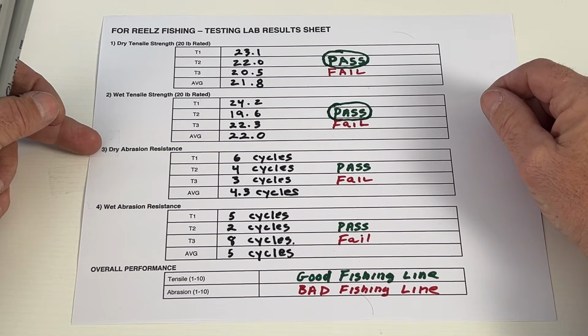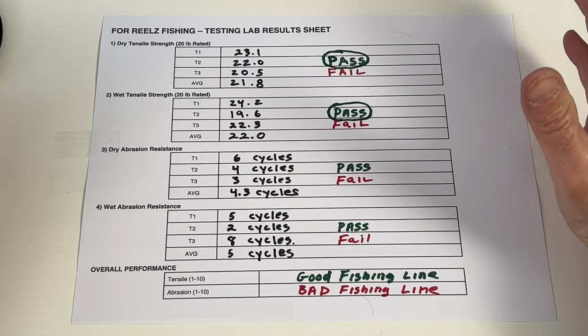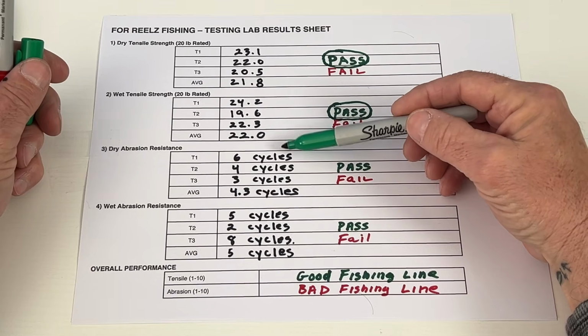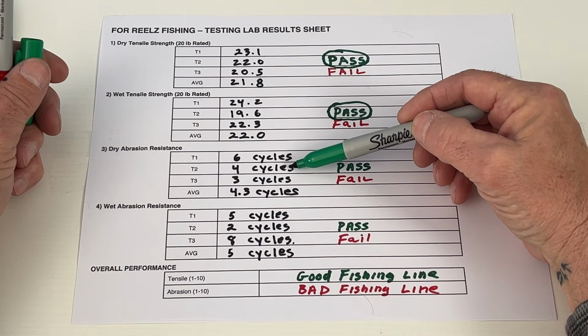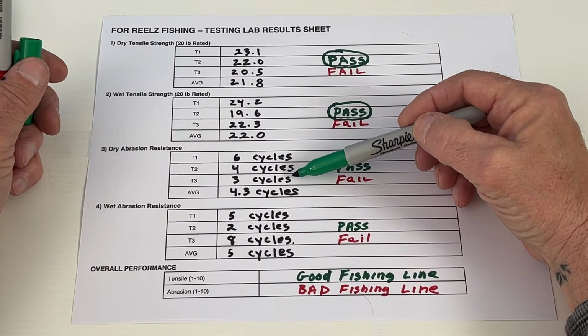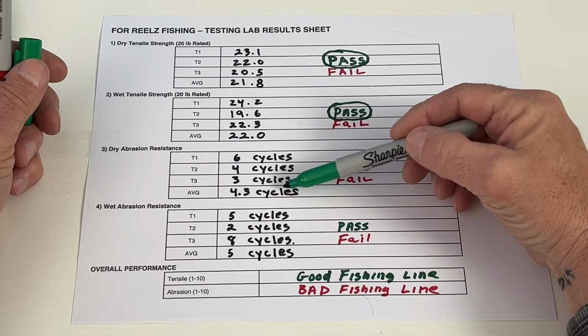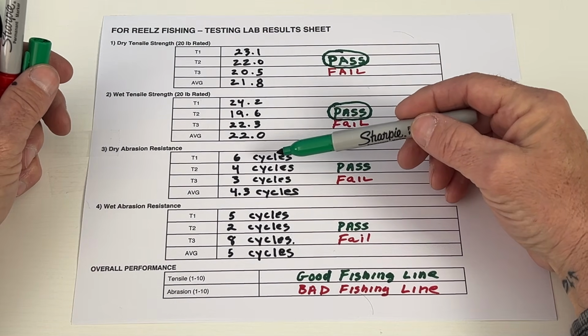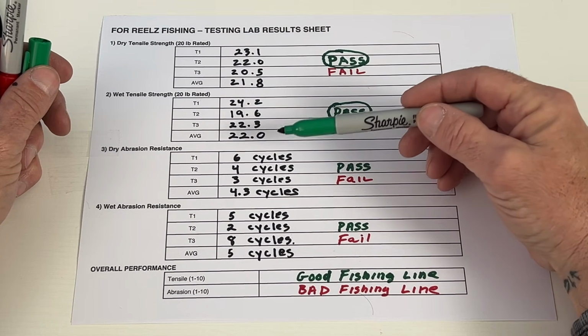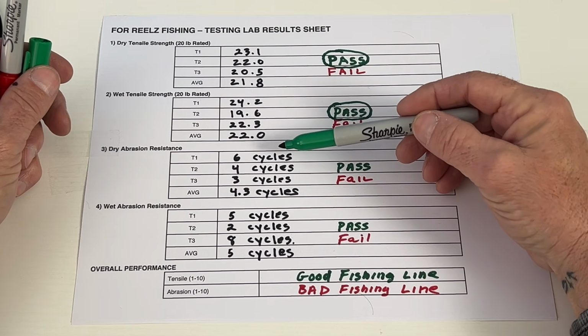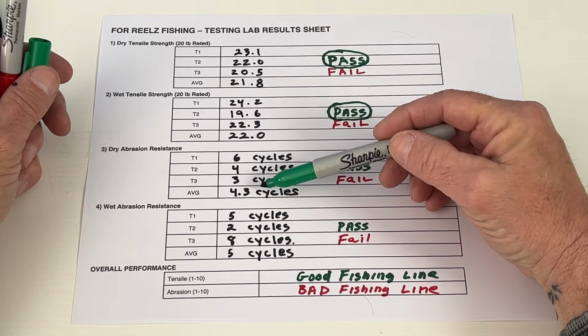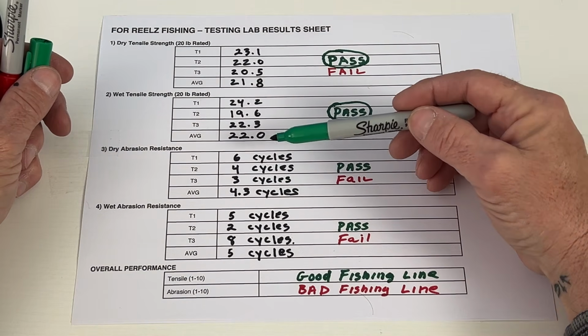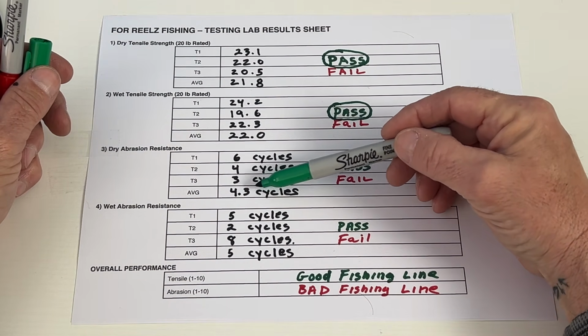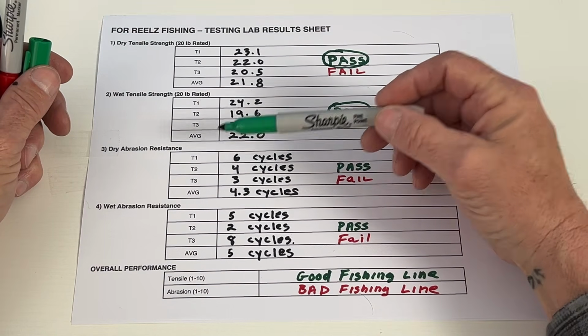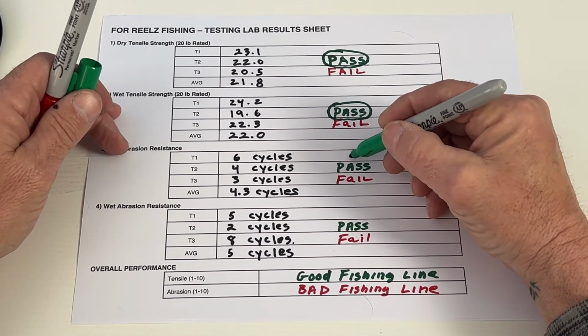Third, we did a dry abrasion resistant test. And we did that on some of the actual types of structure you will find at your fishing spot. Test 1 went 6 cycles, test 2 went 4 cycles, and test 3 went 3 cycles, for an average of 4.3 cycles. When I'm testing abrasion resistant tests on the actual types of structure you'll find at your fishing spot, like sharp rocks, anything above 3, in my book, is a pass. So this averaged out at 4.3 cycles of the dry abrasion resistant test. So that did really well.